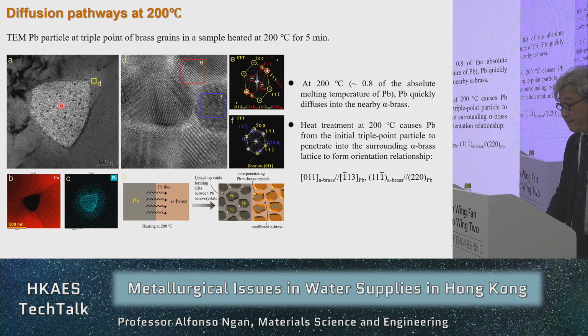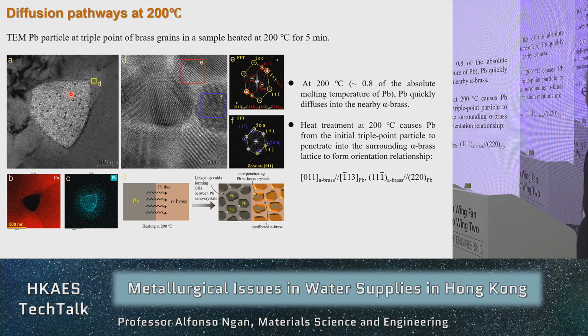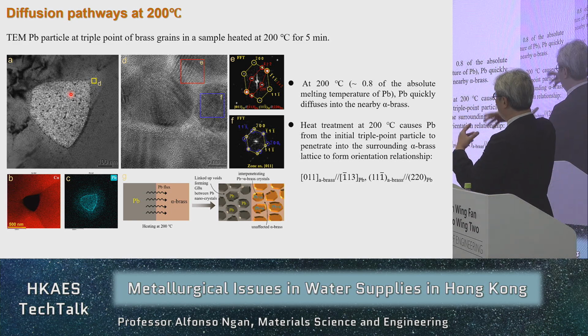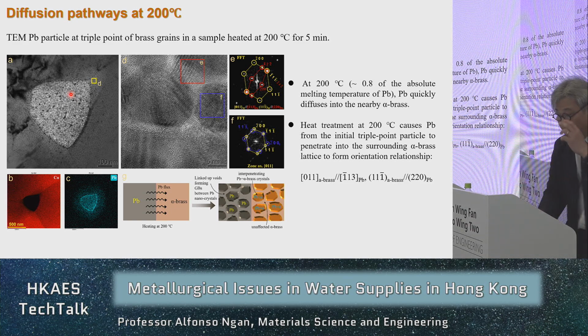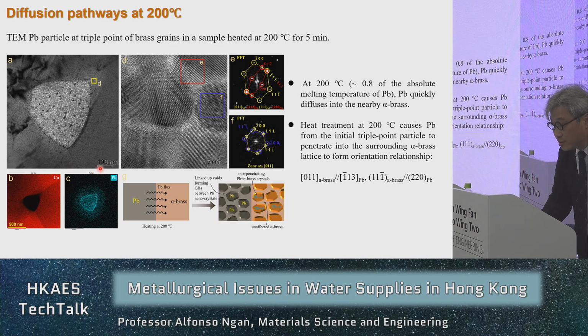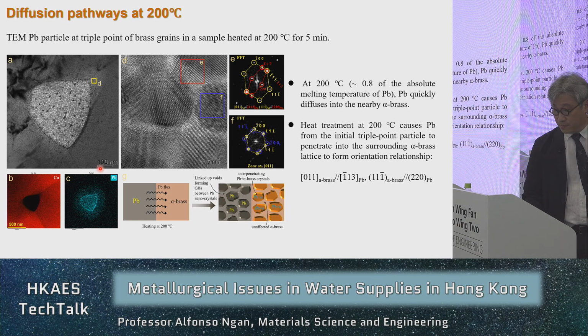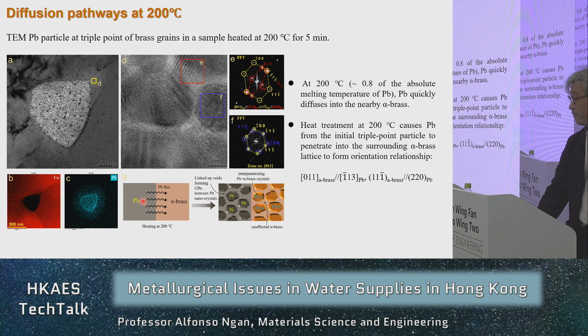But after heating for some time, so that was originally one solid lump of lead, but after heating at 200 degrees Celsius for some time, you begin to see some cracks generated. The lead particle is broken up into many smaller ones, each about 10 nanometers. We think the mechanism is because of lead diffusion. The lead atoms from this lump are diffusing outside, all right?